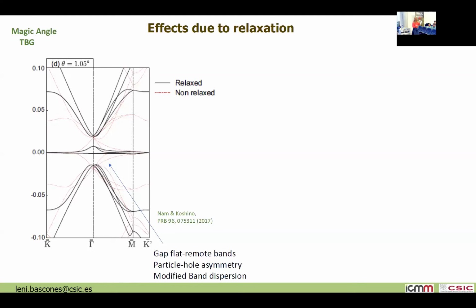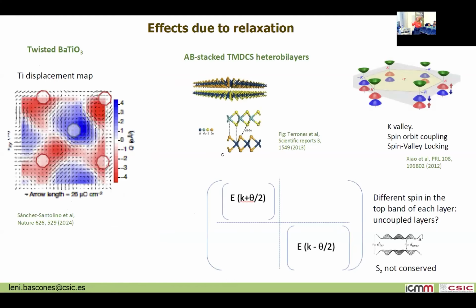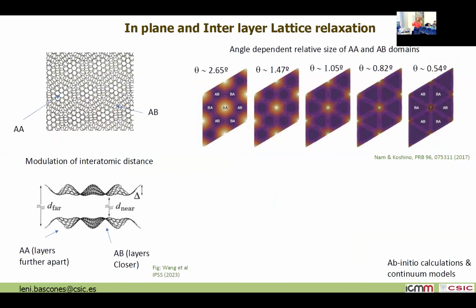I know that there are small effects, and most of the time they are thrown away. But here, what I can tell you is that this has been observed, if you are interested. This fact that you have very large AB domains and a very small AA region has really been observed. Now that's at a very small angle, and the stacking is mostly the Bernal one.